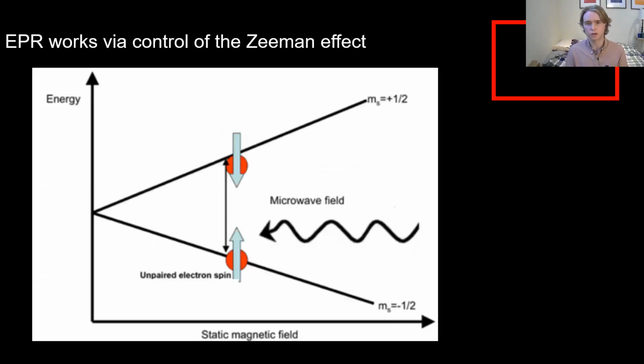Now, the reason that it generates this curve is due to something called the Zeeman effect. So, in absence of a magnetic field, when there is no magnetic field, the spins of the electrons, both up and down, will be at the same energy level. But as we start to apply a magnetic field, we begin to start seeing what's called the Zeeman effect, where the energy level between the up spin and the down spin starts to break apart. One moves to be lower in energy and one moves to be higher in energy. And so we can actually then access this very, very small change in energy with a microwave. So we can use a microwave to perturb the low energy spin into the high energy state, and then we can also watch it relax. And that's kind of the basis of how EPR works, by splitting the energy level of these spins. Of course, we have these single electrons that we're able to perturb, and then we can use that to create our spectra that we're interested in.